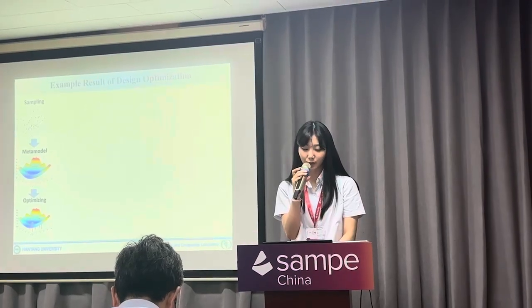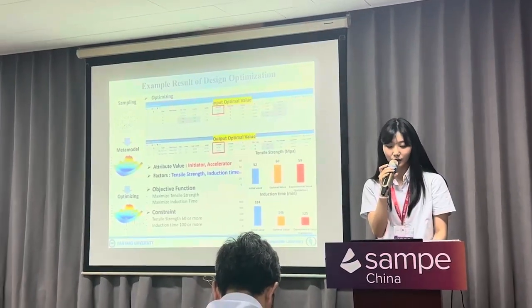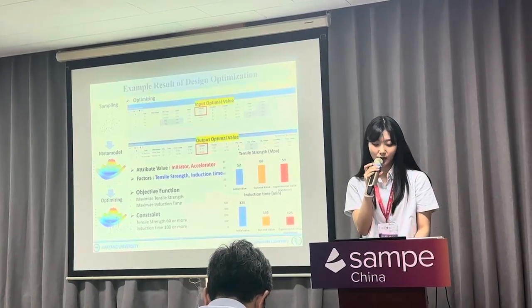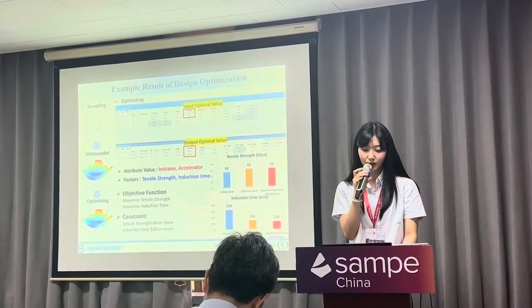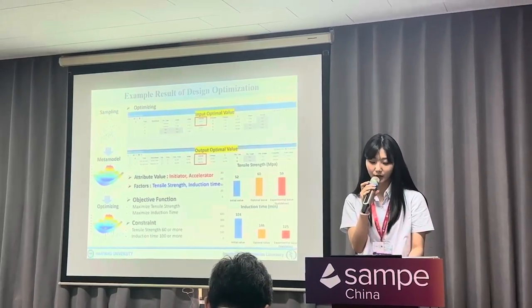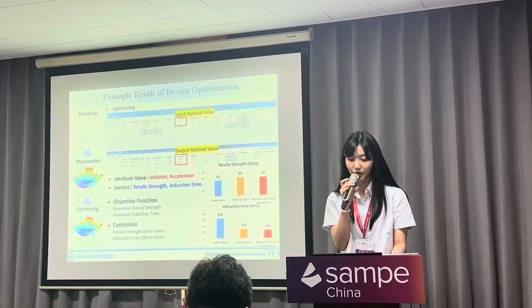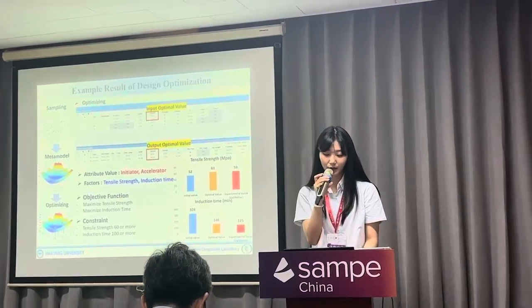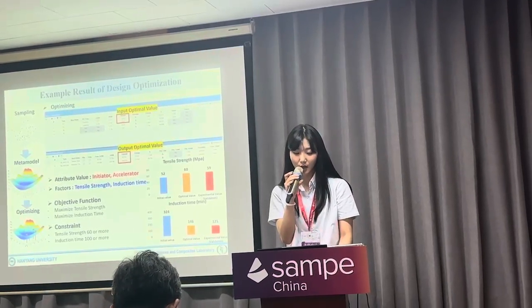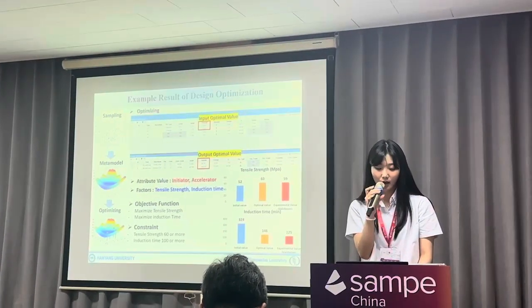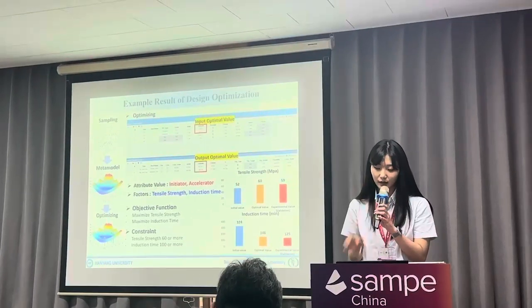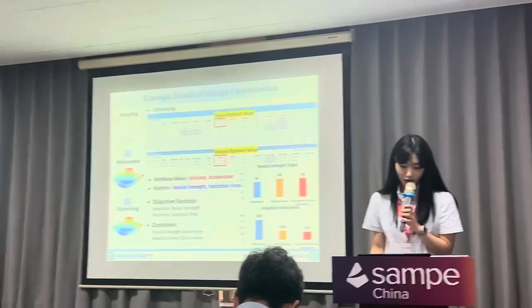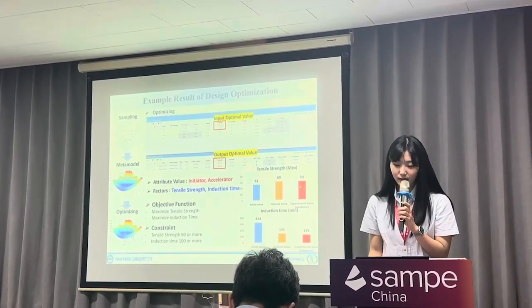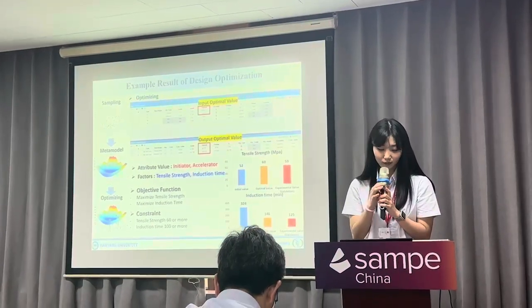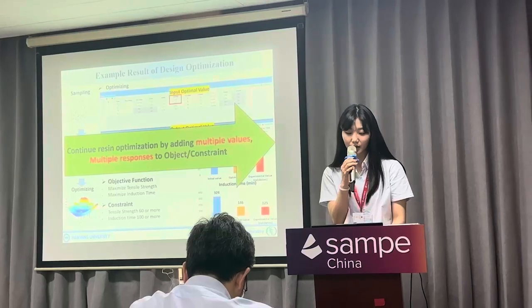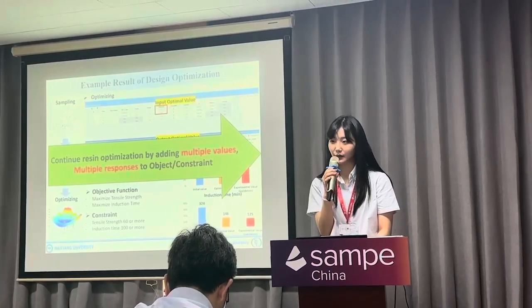Using the previous meta model, we can perform design optimization. In the optimizing process, we need to define variables. In this example, they are initiator and accelerator. And then we set objectives and constraints. An objective chooses a functional combination of variables to maximize or minimize, and constraints express combinations of variables that must be satisfied by acceptable design alternatives, as equations or inequalities. By doing all of these settings, we can get the expected optimal value that satisfies the condition. There is an initial value that I conducted before, and the optimal value is here. Then we can test the experiment value for validation. So I proceeded to continue resin optimization by adding multiple values and multiple responses, including viscosity and others.